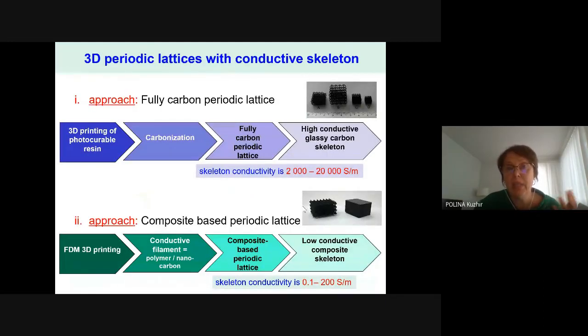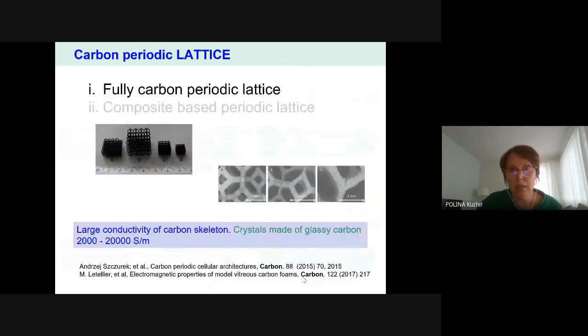In order to play with 3D geometry, we propose two approaches. We could deal with a fully carbon periodic lattice composed of a highly conductive skeleton, or with a periodic lattice whose skeleton is made of a composite based on carbon with intermediate conductivity from 0.1 to a maximum of 200 Siemens per meter. Today I will try to tell you about the possibility to use the fully carbon highly conductive skeleton, and tomorrow, when I speak about composite materials, I will stop briefly on the second approach.